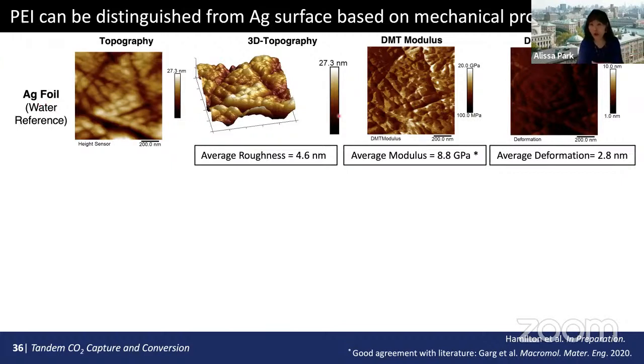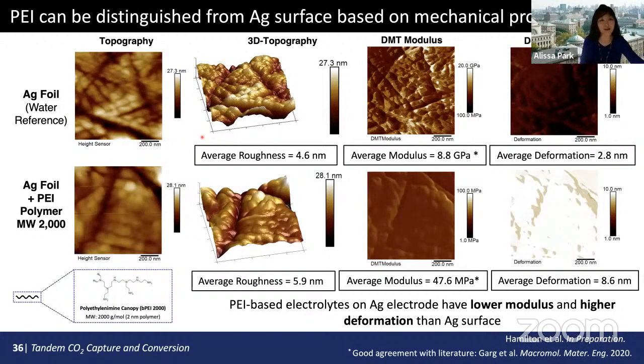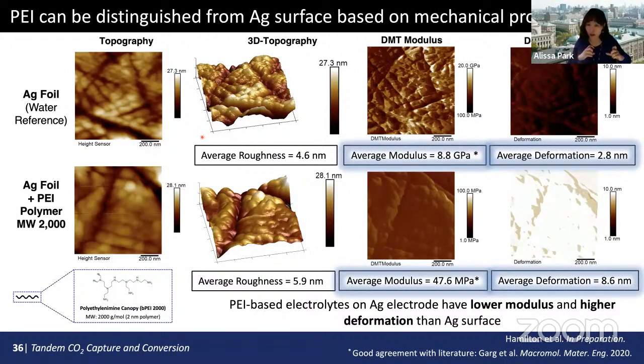There's some roughness to it, and you can actually get the roughness measurements as well as modulus and deformation. And modulus and deformation are going to tell us, compared to this base case, what's on the surface. If there's a specific adsorption of polymers onto the surface, you will have very different modulus and deformation, which we saw. So this is the second system with silver foil with PEI in the solution, and you can see that it's much softer on the surface, so there's a higher deformation, and modulus is lower too.